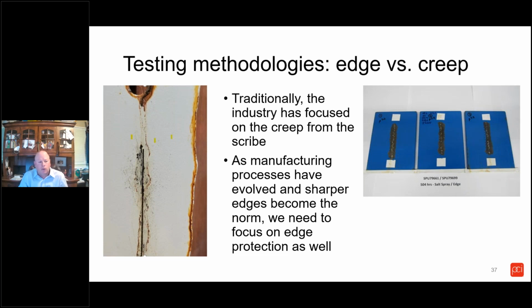The white panel, which was about 2,500 hours, looks very good from the scribe—very little creep, if any—but there is significant corrosion on the edge of that panel. Whereas the blue panels, the edges look good, but there is significant creep away from the scribe.